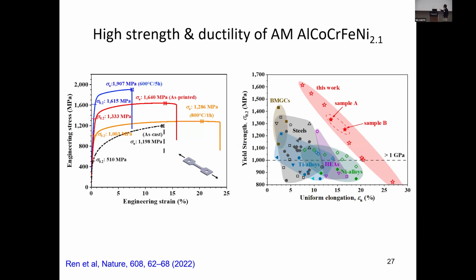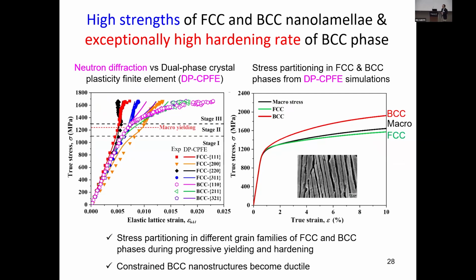So we have a very good combination of high strength and high ductility. They are much better than the strength and ductility combination from the same alloy, but produced by the conventional directional solidification. So you can see, this strength and ductility combination is outside the conventional regime for other competing alloys and eutectic alloys. So it's a dual-phase microstructure.